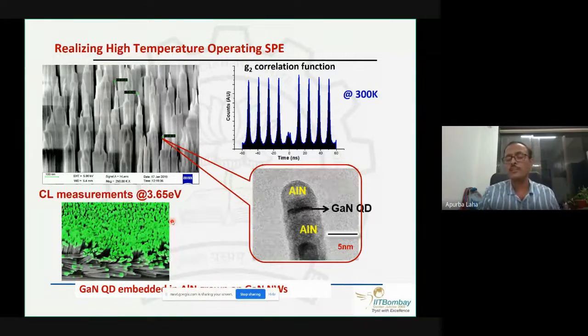By doing that, you are ensuring that those quantum dots are truly confined in all three directions, and only then are you able to see the correlations even at room temperature. No other system would show G2 correlation at room temperature. The only challenge here is to put the gallium nitride quantum dot, or indium gallium nitride quantum dot if you are working in the visible range, at this range. So with that, I think it's too heavy at this point, so I'm just going to end.